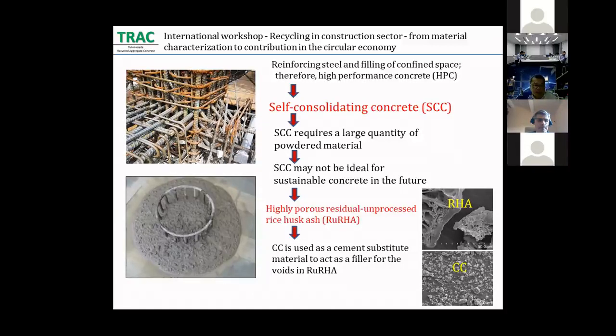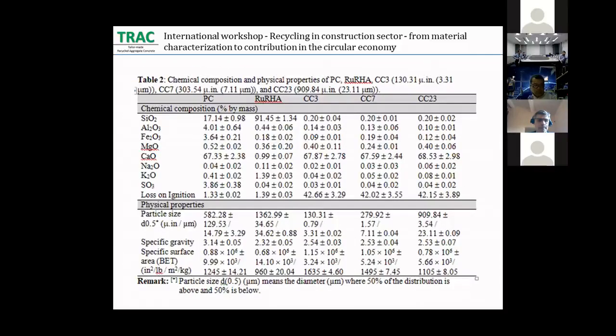Therefore, additional fine aggregate replacement material can be incorporated to fill the voids within the rice husk ash particles. Moreover, its utilization as a supplementary material in concrete is increased. Both the intrinsic properties and the cost of the material should be practical. To investigate the properties of self-compacting concrete mixed with rice husk ash at percentage replacements of 0 and 20%, rice husk ash obtained from a rice husk-fired power plant in Thailand was used without any processing or treatment to replace fine aggregate or river sand.